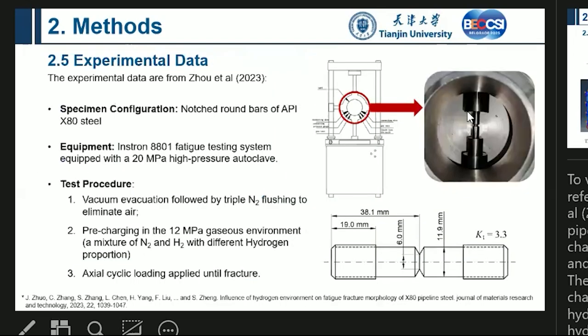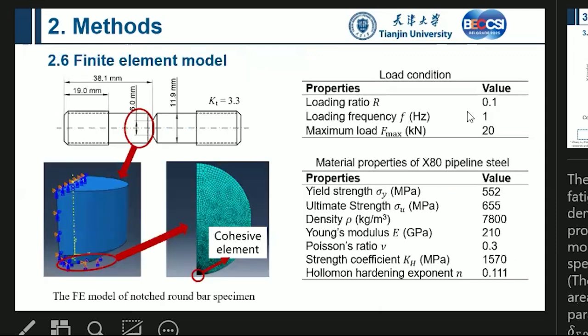Then we first compare with the experimental data, and this experiment was performed by Zhou in 2023. This is the experimental model, the loading condition, and also the material properties. And this is our finite element model, and here we put the cohesive element.